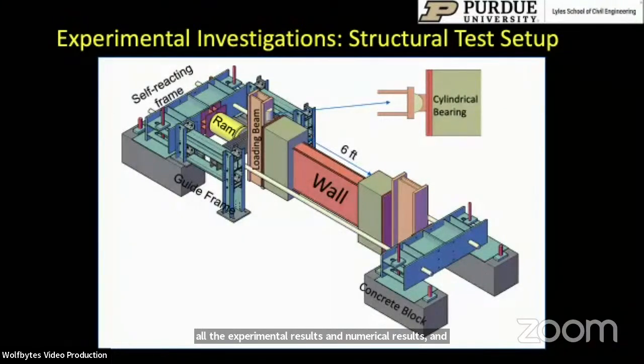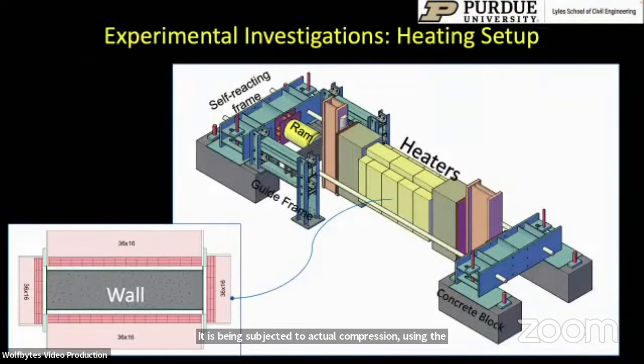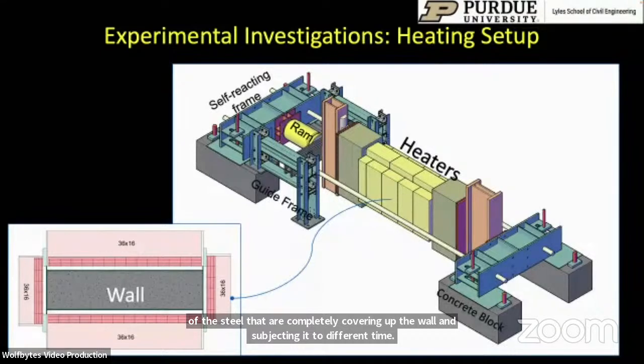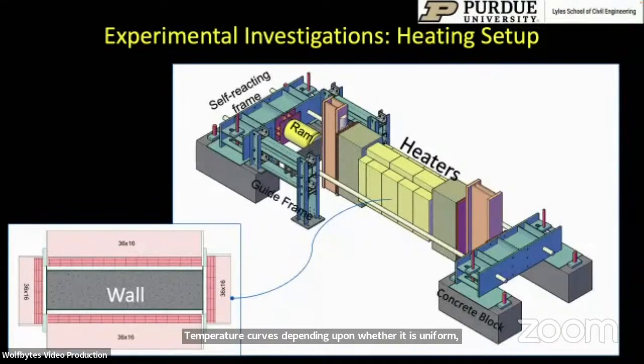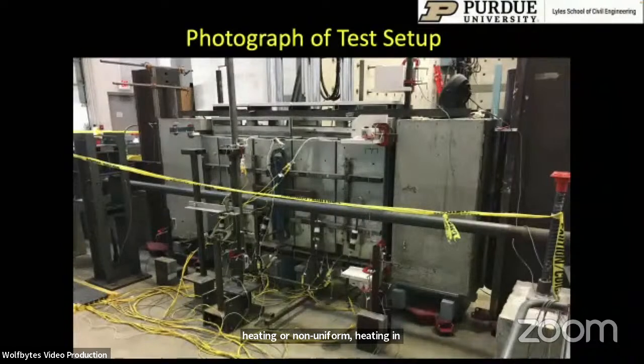This is showing you a structural test setup for the wall. It is being subjected to axial compression using the self-reacting test setup. And then it is covered by what are ceramic fiber radiant heaters, which I can control the temperature versus time response of on the surface of the steel, that are completely covering up the wall and subjecting it to different time temperature curves depending upon whether it is uniform heating or non-uniform heating. A photograph of this test setup in the laboratory is shown here. You're seeing the heaters that are completely enveloping, so you can't really see the wall. It's behind the heaters.